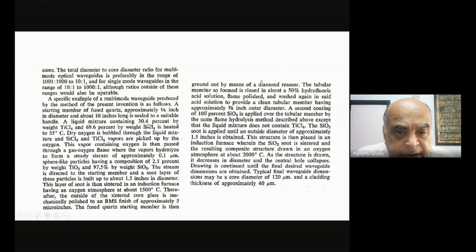A liquid mixture containing 30.4% by weight TiCl4 and 69.6% by weight SiCl4 is heated to 35 degrees centigrade. Okay, that's what they're doing. Dry oxygen is bubbled through the liquid mixture, and SiCl4 and TiCl4 vapors are picked up by the oxygen. Okay, so basically what is happening is that SiCl4 will get converted into SiO2, and TiCl4 will get converted into TiO2. This vapor containing oxygen is then passed through a gas oxygen flame where the vapors hydrolyze to form a steady stream of approximately 0.1 micron sphere-like particles having a composition of 2.5% by weight TiO2 and 97.5% by weight SiO2. Now, this is very interesting.